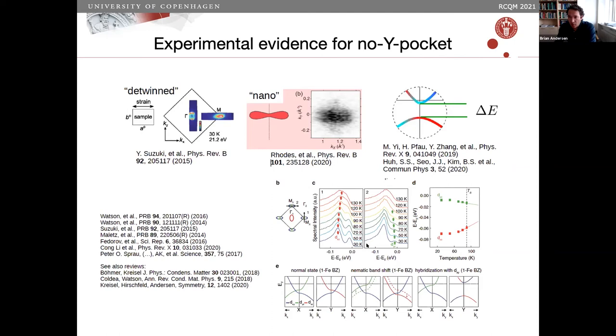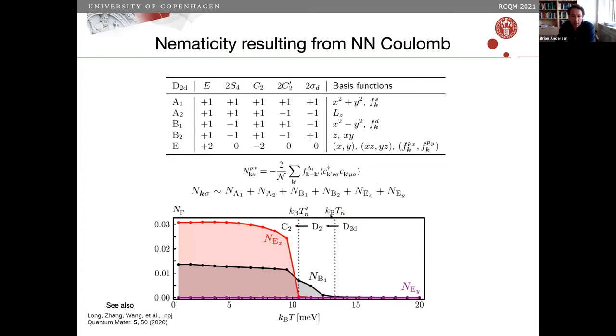In my opinion, a quantitative discussion doesn't make a lot of sense at this point because we did not include initial squeezing from U and J, and all these numbers may depend on the initial band structure — as explained in earlier talks, this initial dispersion is way too large. So all these effects should be built on top of a much more renormalized band already from U and J. What I do want to say is that the symmetry analysis of the mean fields is robust. What we should really do is take our calculated mean fields and decompose them in the irreducible representations allowed in D2d, and that's what we did.